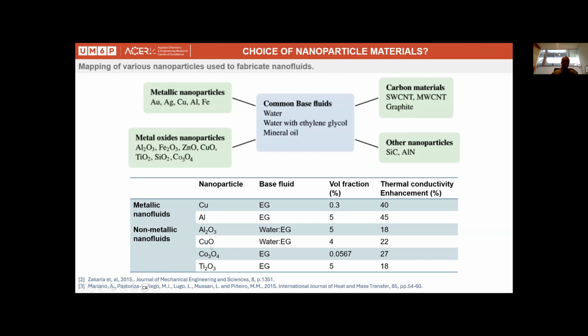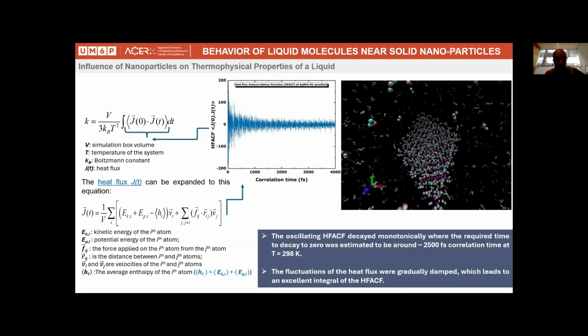But again, the volume fraction is higher than copper here, which means copper is better than aluminium in this case. For oxides, of course, they have lower thermal conductivity compared to metals. So that's why we can see the thermal enhancement here is quite lower than metallic nanoparticles. But anyway, one should test different materials. If I'm looking at oxides like aluminum oxide, it's cheaper to make, with 18% enhancement at 5% volume fraction. It looks good to me because the cost of making aluminum oxide is quite lower than other kinds of materials. But anyway, we are trying at ACER here to implement some plans in order to test different materials from the periodic table so we can find out how we can do that.